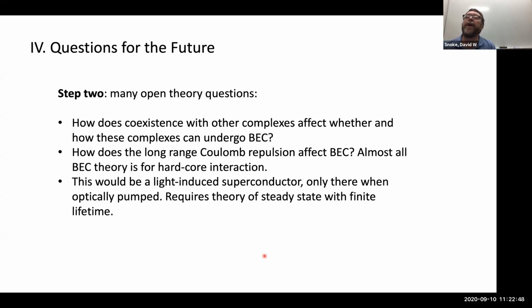In general, the theory of a Schafroth superconductor is not worked out in anywhere near the detail that BCS is, because no one's ever seen one. But in general, you've got long-range repulsive interactions between all the particles. And that is going to lead to some renormalization of the properties of the BEC. And so the theory of a simply charged BEC with long-range interactions is not well worked out in the literature. So that's a very basic theory project. Maybe it doesn't make much difference at all. Maybe it does. This is also a steady state. We either pump it with light or with electrical injection, but either way, it's going to be a steady state type system. And so a lot of the theory that's been worked out for excitons and polaritons would apply in this case as well.